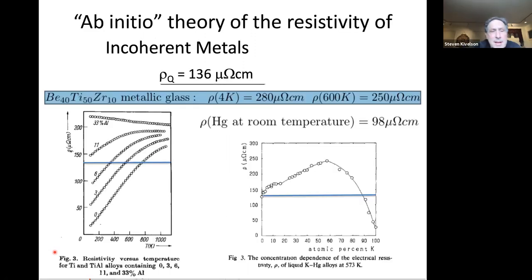So let's look at some things. Here I've just reminded you what the quantum of resistivity is in three dimensions. It's 136 micro-ohm centimeters. So I looked up various things. I found some metallic glass. In a metallic glass, you wouldn't particularly expect emergent quasi-particles. And indeed, the resistivity at 4 Kelvin is 280 micro-ohm centimeters, well, more or less within my factor of 2 of the quantum of resistance. And it's only very weakly temperature dependent. By the time I get up to 600 Kelvin, it's 250 micro-ohm centimeters. That I consider a success.